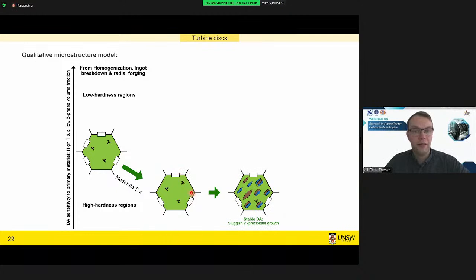We retain the high dislocation density and the delta phase volume fraction, which is in favor of a very fine distribution of our precipitates. I call this a stable direct aging in this case.